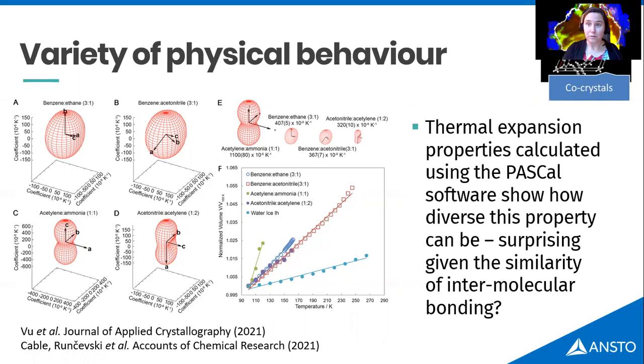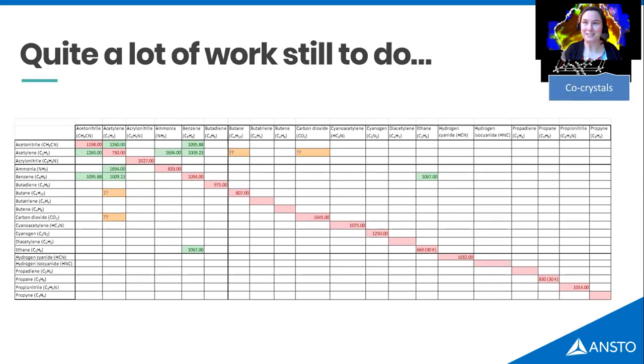So there's a lot more to do. Here is the paired up diagram, and in each of the sections I've coloured in where we've got the material and the structure, and the number is its density in kilograms per cubic meter for the material at 100 Kelvin. I'm trying to standardize it all and understand, at least from a beginning perspective, the relative density of these materials. That's the first basic: if they all pile on top of each other, which one's going to sink down to the bottom and which one's going to bob up to the top in terms of buoyancy over a processing time scale.